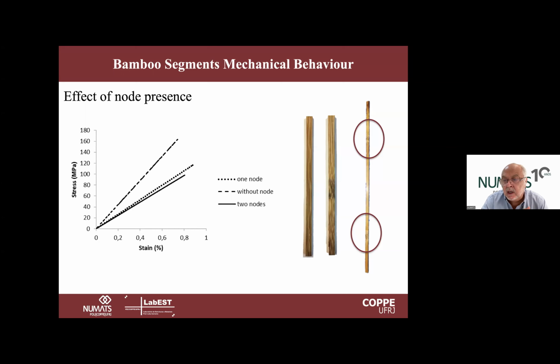And we did here a test with no nodes, so just using the internodal length, and then with one node in the center, and then with two nodes. And what we saw here was that there is a slight decrease when we go from 1 to 2 nodes. But the main reduction is with the presence of one possible source of defect where we initiate the failure.